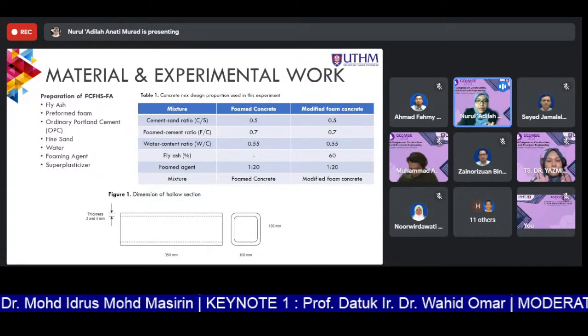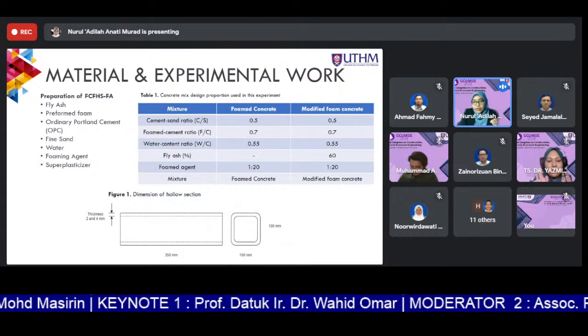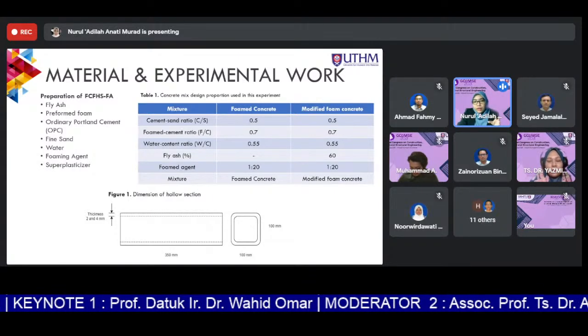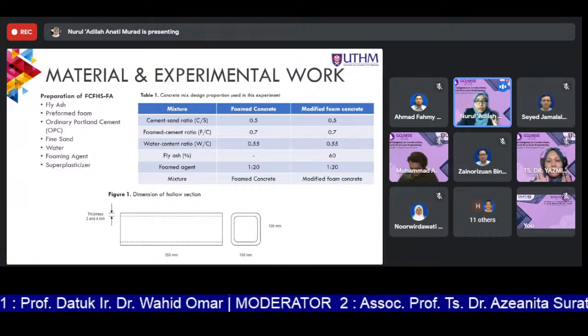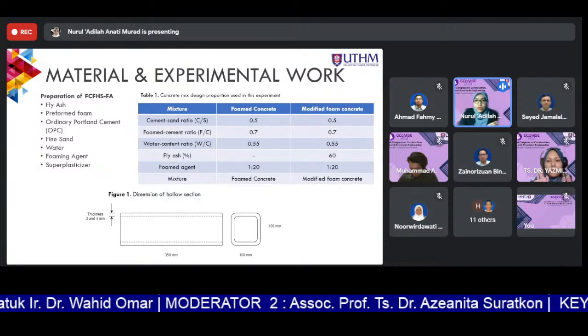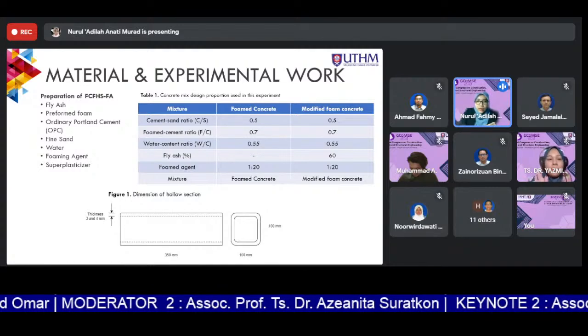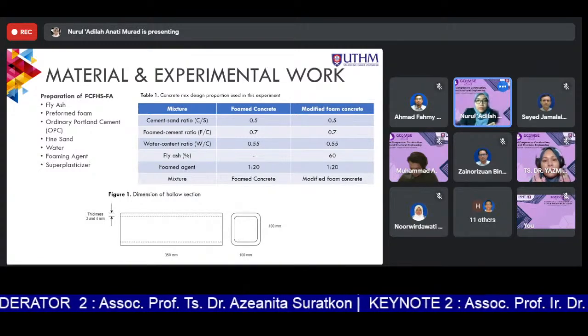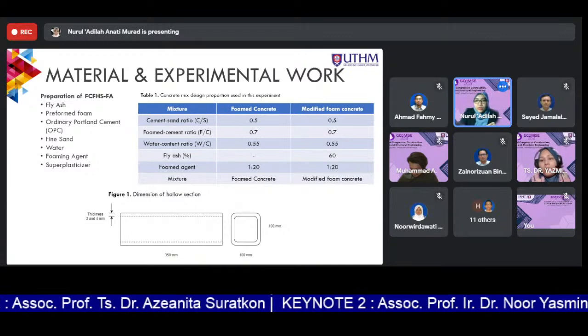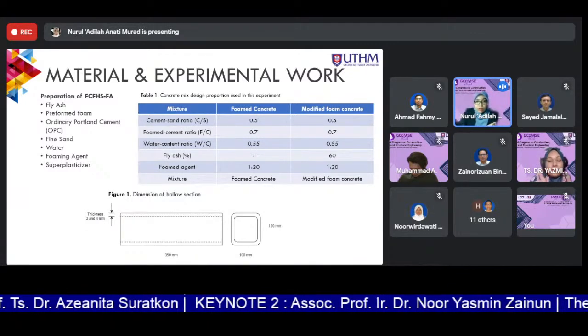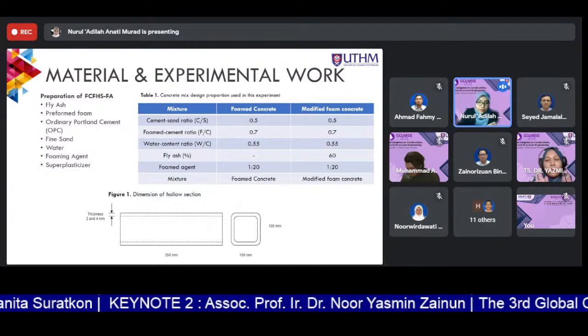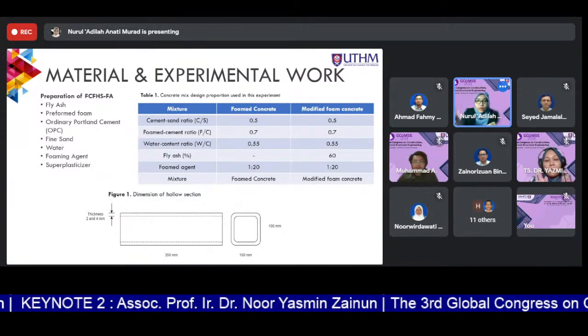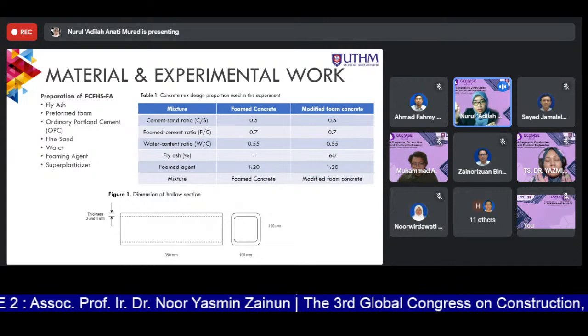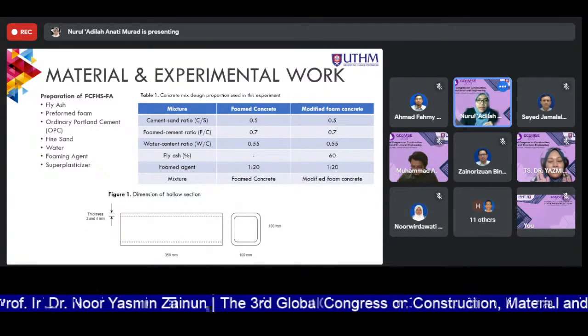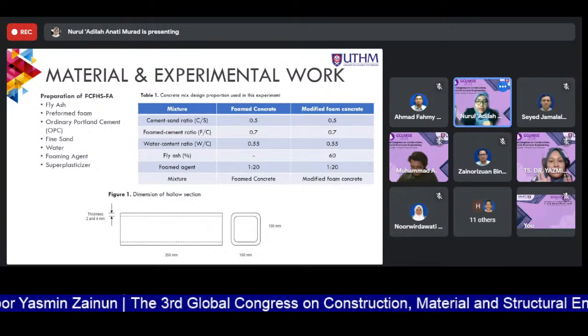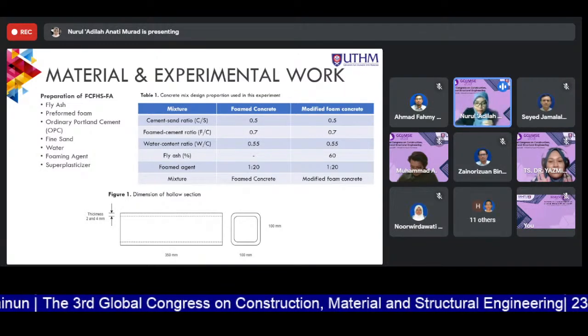And this table is the concrete mix design preparation that has been used in this experiment, where the cement ratio for the foam concrete is 0.5 and for the modified foam concrete is 0.5, while the foam cement ratio for both of the mixtures is 0.7 and the water cement ratio is 0.55. However, the modified foam concrete used 60% of fly ash, while the foam concrete uses 0% of fly ash, and the foaming agent is 1:20.